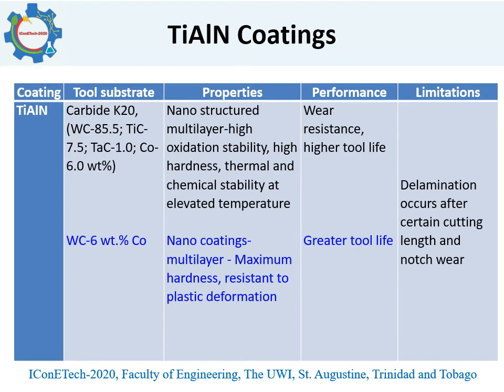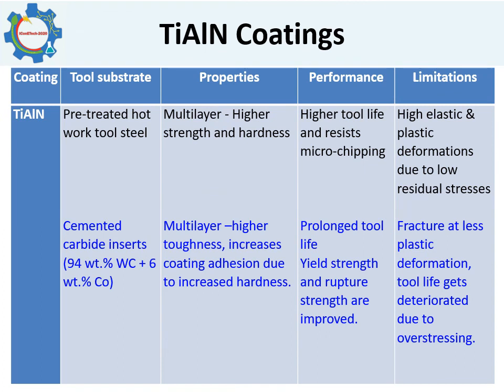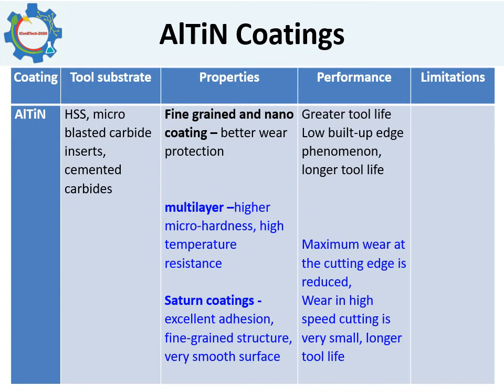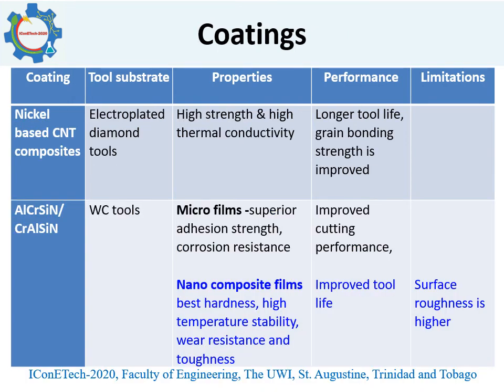These are some other coatings, and unfortunately the time given to me, 10 minutes, does not allow me to go into the details, but you can notice that these have improved wear resistance and higher tool life, and generally delamination still is a problem that one has to consider. Most of these coatings have higher tool life, and generally they are with a low built-up edge phenomenon. Typically, tool life of coated tools is almost 3 times or more, but of course the cost is equally higher.